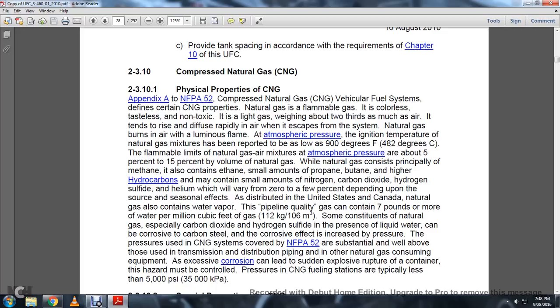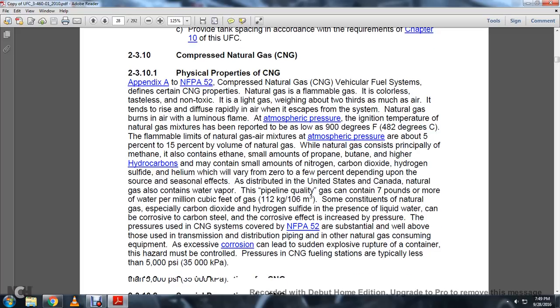Liquid water can be corrosive to carbon steel, and the corrosive effect increases with the pressure. The pressures used in compressed natural gas systems covered by NFPA 52 are substantial, well above those of transmission and distribution piping and other natural gas consuming equipment. Excessive corrosion can lead to sudden explosive rupture of the container, and the hazard must be controlled. Pressure of the continuous compressed natural gas fueling station is typically less than 5,000 psi.